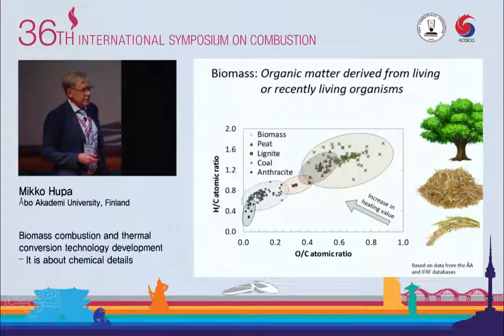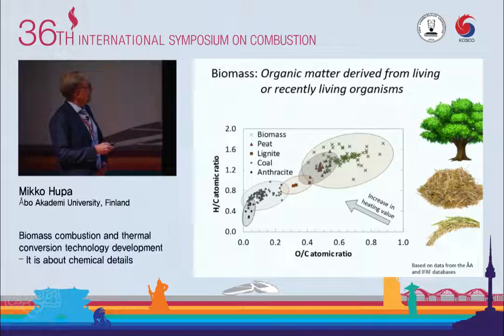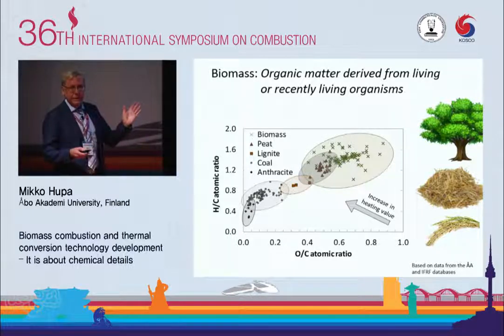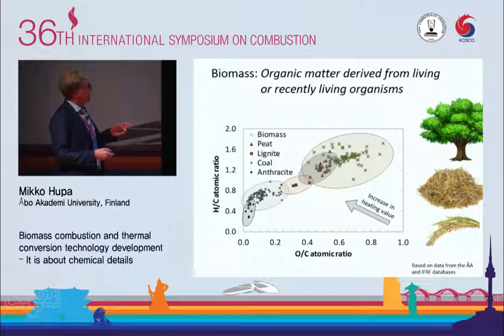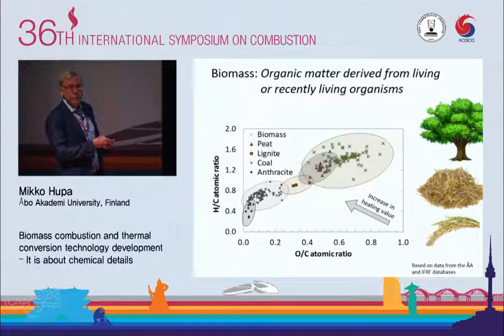The graph which is used for coal, where we have a hydrogen-oxygen plot, hydrogen to carbon ratio, oxygen to carbon ratio, shows quite nicely how biomasses relate to coals. So in this kind of graph, anthracite coals are down here, of course, very low hydrogen, very low oxygen. The younger coals will place themselves here, brown coals, lignites further ahead.